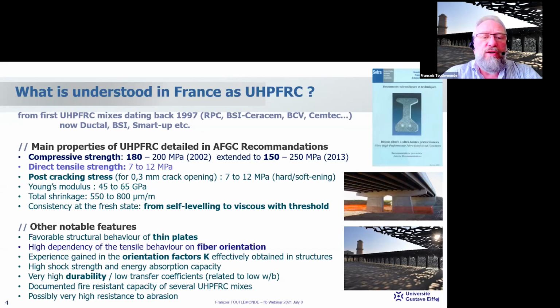This is described by an orientation factor, a factor called K, that is obtained in the structures. Other important features: the high shock strength, the capacity of energy absorption, and the very high durability and low transfer coefficients, which are related to the low water to binder ratio.